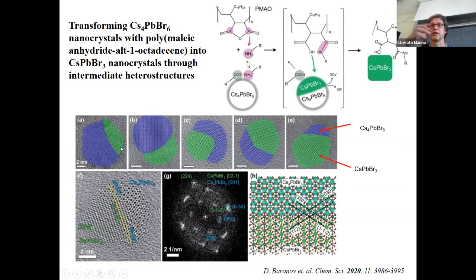This transformation is gradual in this case, so you can actually capture the transformation of the nanocrystals at intermediate stages. And what we find here is that these structures are epitaxial, and the epitaxy is given by the continuation of the cesium cation framework.